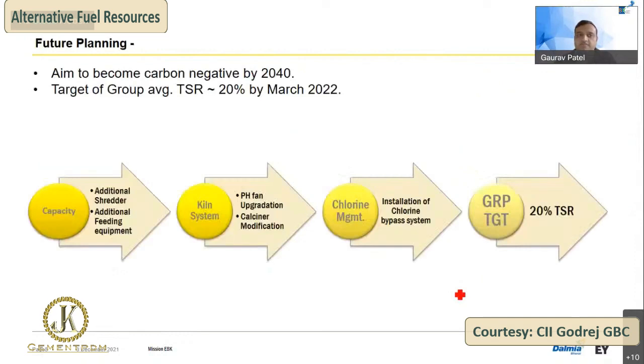For that, our future planning is to aim to become carbon negative by 2040, with a TSR target of 20%. We are planning to install an additional shredder, mostly a secondary shredder, to reduce the size further from 70 to less than 40, so that in the available calciner residence we can have higher green fuel feeding. Additional feeding equipment is also needed, because the ATS extractor has a capacity of 25 tons per hour, and we need to increase it further to cater to the increase of heat consumption and additional volume because of moisture.